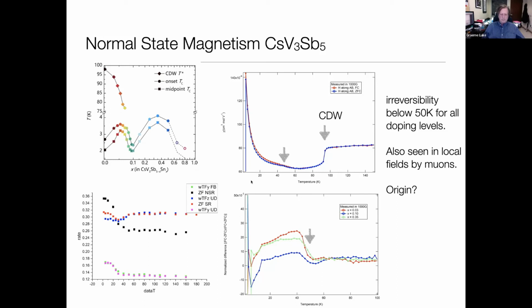If we plot the normalized difference between the field cooled and the zero field cooled, so we just take the difference between the two of them and divide by their sum, you see above about 50 Kelvin, it doesn't matter how you get there, the difference is 0. And then below about 50 Kelvin, for all the different doping levels of our samples, we start to see the emergence of this history dependence in the susceptibility at lower temperatures. And of course, down here at TC, everything goes haywire, but that's fine. So we're seeing some magnetic behavior, a spontaneous change in the internal magnetic environment, which is fairly weak but non-zero, occurring in bulk measurements of the material at lowest temperatures.